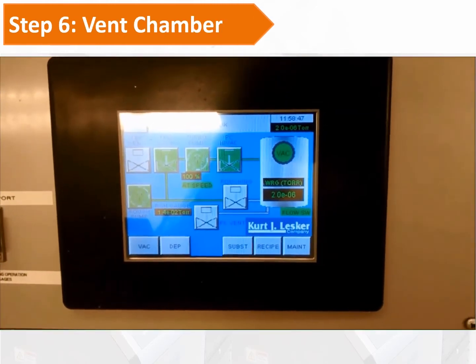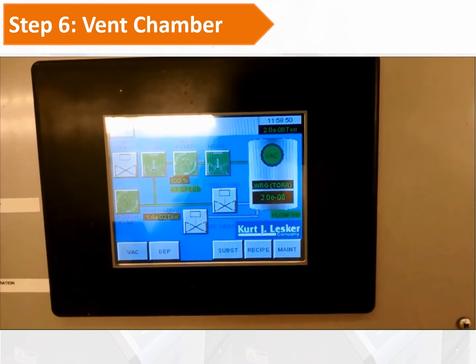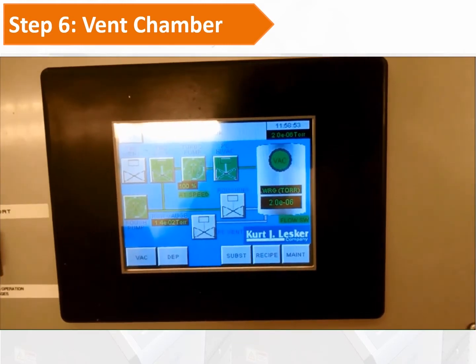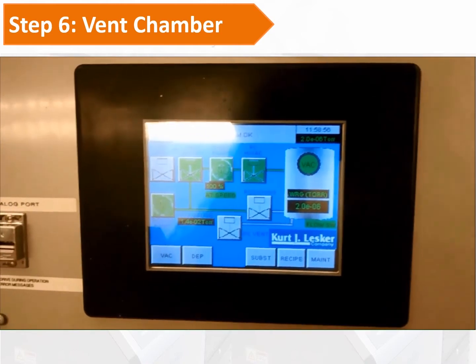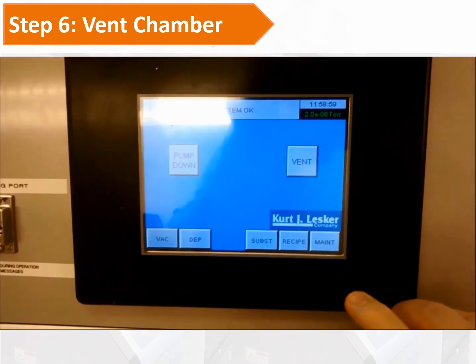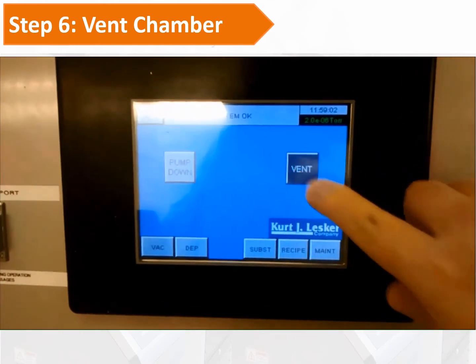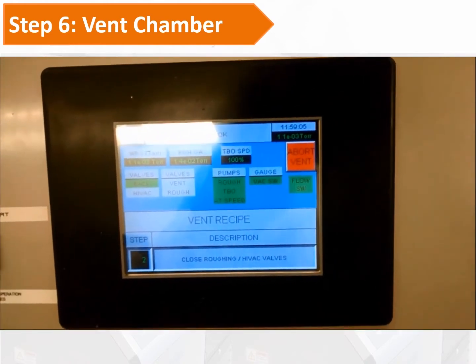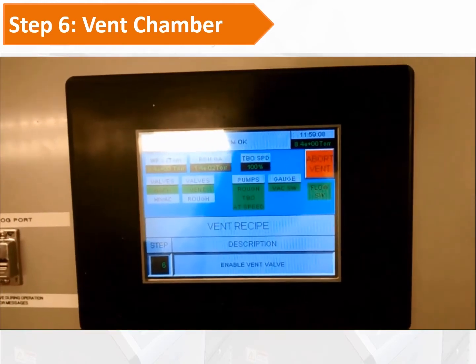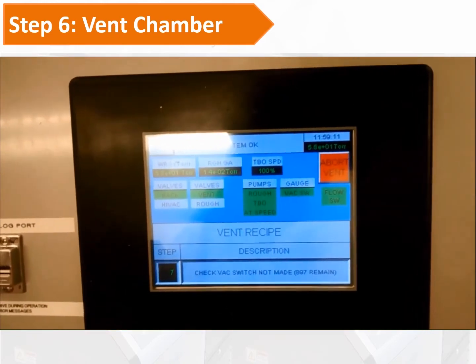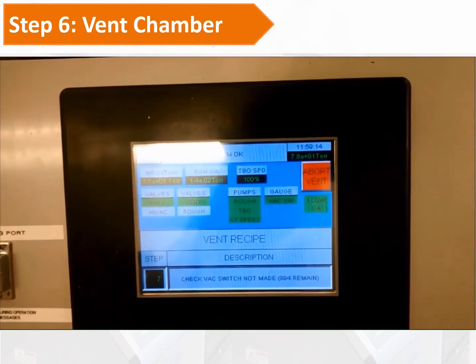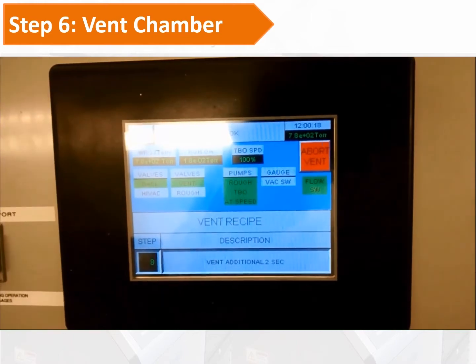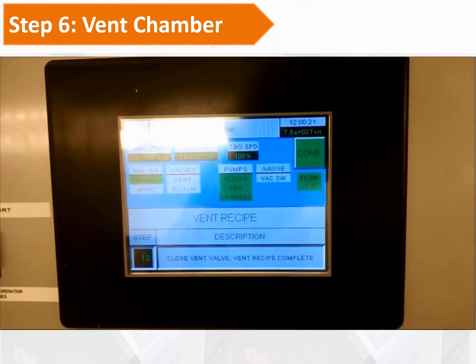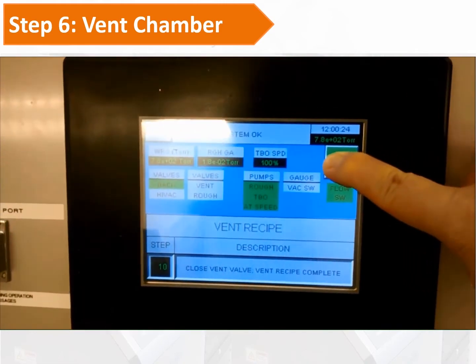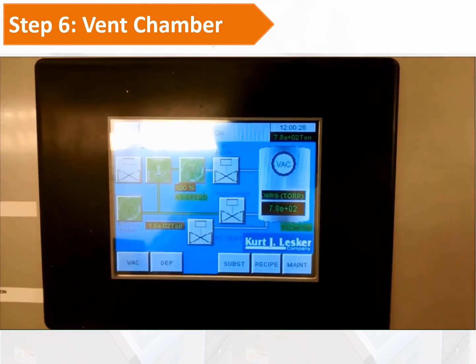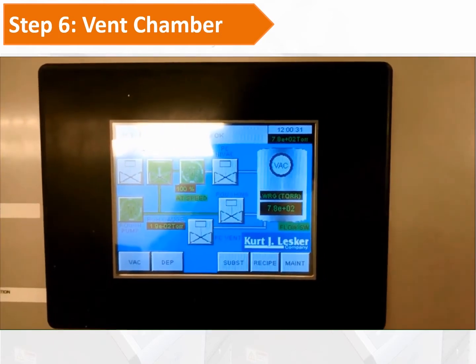Step 6, vent chamber. Wait around 10 to 15 minutes after your deposition is completed, and press the recipe button in the control screen, and then touch the vent button to run the vent recipe. It also needs around 1 to 2 minutes. And when it is completed, the green done button will show on the screen. And then press the done button. It means the chamber has reached atmospheric pressure, and now we can open the door to unload your sample from the chamber.